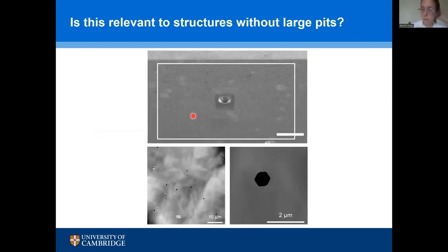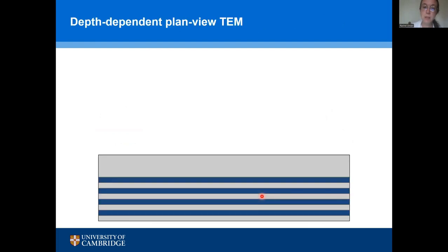Is this actually relevant at all, except in these structures where we've accidentally created these great big pits, which you can see here in the SEM and here also in the AFM? Because as I say, this isn't good material. Well, what we needed to do was probe more deeply through our real device structures. And we've done that using some transmission electron microscopy experiments, because what we wanted to find out was whether these large fields were present in our real device structures. So what we've done to probe that in the TEM, rather than using the FIB that I showed earlier,